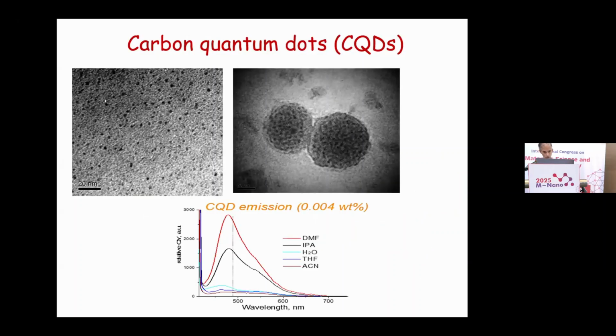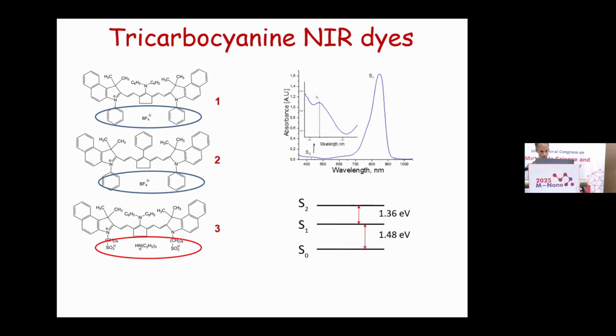So in this work, we used commercial carbon nanodots. You can see here the morphology of these nanoparticles and the photoluminescence spectrum of these nanoparticles, which have different quantum yield depending on the solvent. On the other hand, we use infrared dyes with different terminal groups in order to interact with carbon nanoparticles.